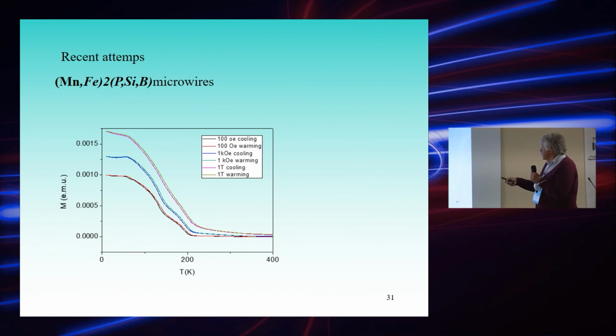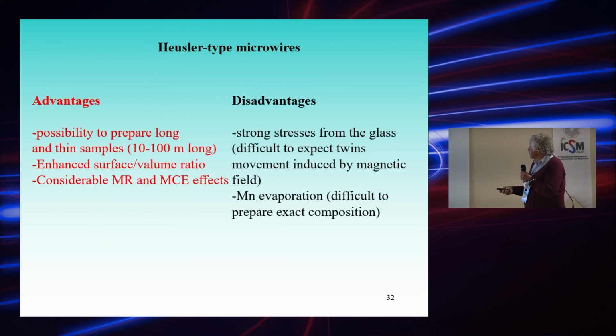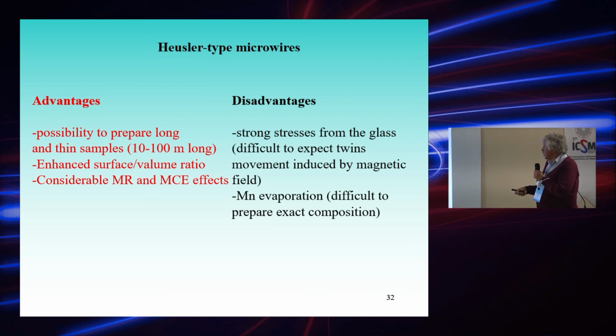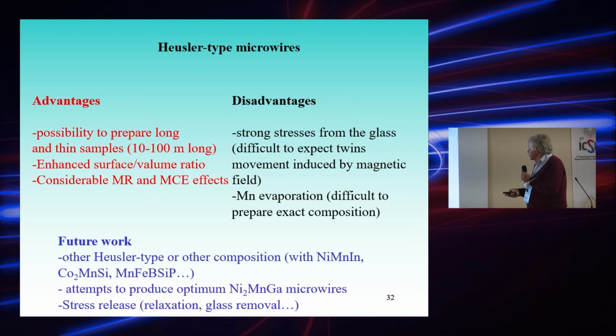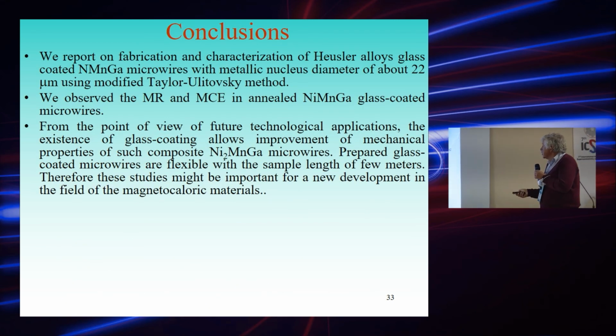And this is maybe the last slide. Just this week we prepared this new composition, not a Heusler alloy, but it could also be suitable for applications. The advantages of this possibility: we can prepare long microwires with enhanced, first of all, giant magnetoimpedance ratio, considerable magnetoresistance effect and magnetocaloric effect. The disadvantages: we need to somehow fight the strong internal stresses and manganese evaporation.